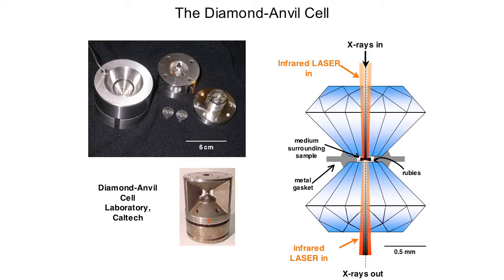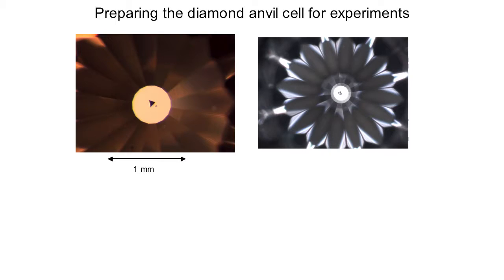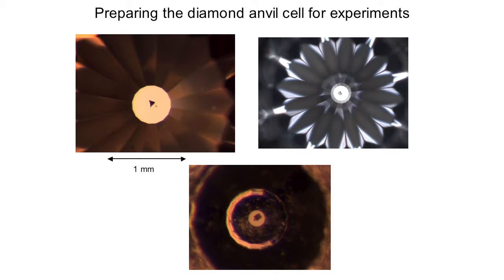So you can also see where we probe the sample with X-rays, and this is a simple scattering environment where the X-rays come out in the same direction as they come in. And we also have an infrared laser that is collinear with that probe so that we can heat the sample while we measure its properties. And here are a few pictures of samples from the microscope showing the very small size. This arrow is 1 millimeter, and different samples on top of the culet, and then the gasket is lowered down over, say, a nice single crystal of an oxide, representative of Earth's lower mantle.